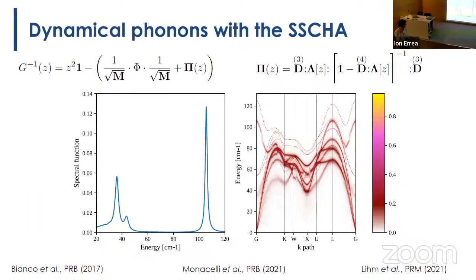Sometimes we can actually calculate these without approximating to a Lorentzian. So we can actually see complex line shapes that appear in some systems. Like in lead telluride, you have a double peak where you expect one peak, and it's not because there is a phase transition, it's because the anharmonic effects are so big that this peak splits in two. So in inelastic experiments, you should see two peaks instead of one, but there is no symmetry breaking. It's just because the Lorentzian shape is no longer true, and you have what we usually call a potato mode.